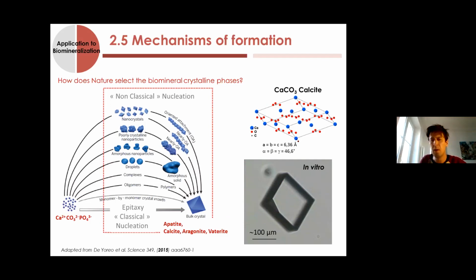But for biological samples, that's not the case. You have a variety of different mechanisms proposed in the literature, and usually you start nucleation with some intermediate, transient phases that assemble, most of the time via an oriented attachment mechanism, and then go to the bulk crystals.